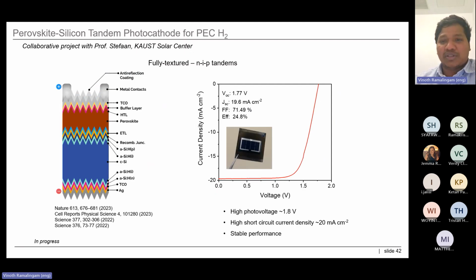And this is one of our previous projects where we had a collaboration with Professor Stefan at the KAUST Solar Center. They are experts in fabricating a fully textured NIP perovskite silicon tandem device. Here is the architecture of the device that they made. The beauty of the perovskite silicon tandem cell is that it can produce high photovoltage, close to 1.8 volt, whereas in the case of water splitting reaction, the thermodynamic potential is 1.23 volt. So when we have such high voltage, you can demonstrate this kind of device for bias-free water splitting reaction. That's where the idea comes in.